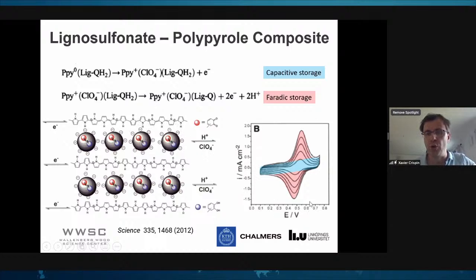If you look at the graph there, the cyclic voltammogram, you see current versus voltage. If you start at 0 volt and you start to charge, you're going to charge your polypyrrole nanowires, making them conductors and carrying charge. This is where you go there. Then after a while, they become very well conducting, and the electric potential of these electrons is going to reach the electronic level of the quinone in lignin. The electrons go from these molecular wires and jump onto the quinone hydroquinone groups here, and there you get the Faradic reaction, the electrochemical reaction, the transformation of hydroquinone into quinone by this electron transfer.